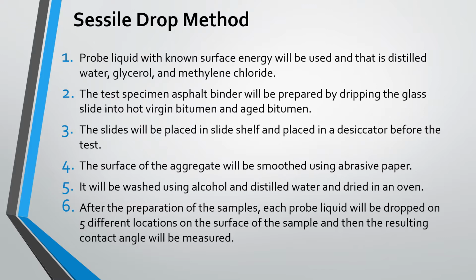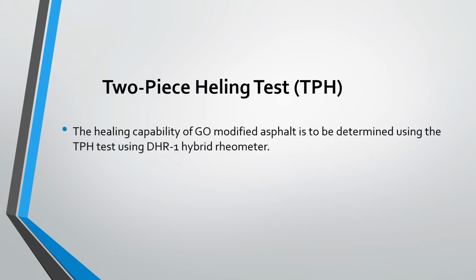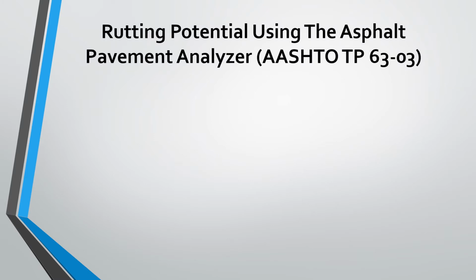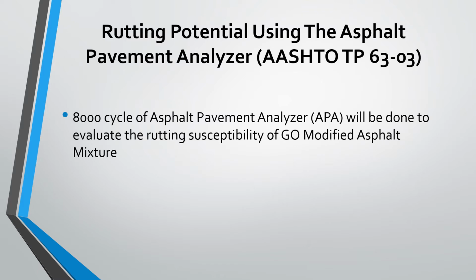The healing capability of GO-modified asphalt is to be determined by the two-piece healing test or the TPH using the DHR1 hybrid rheometer. In order to assess the rutting resistance of the GO-modified asphalt, rutting potential using the asphalt pavement analyzer of AASHTO TP63-03 will be utilized. 8,000 cycles of the asphalt pavement analyzer will be done to evaluate the rutting susceptibility of the GO-modified asphalt mixture. The test will be conducted at 52 degrees Celsius.